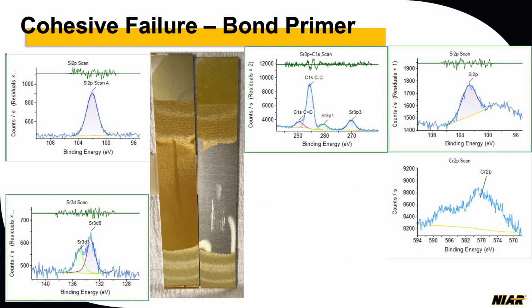Now the next one is cohesive failure for bond primer. So you have basically a primer and you have strontium chromate coating on the metal, which basically completely pulled off. We test on this side, and that's the data on the left-hand side we are seeing. And the metal, where there was complete failure, that data is on the right-hand side. On the left-hand side, we again identified organic silicon, which is at 102 binding energy, and strontium in there. We didn't find much chromate in here to get a good identification, but there was some presence of strontium chromate in this area.